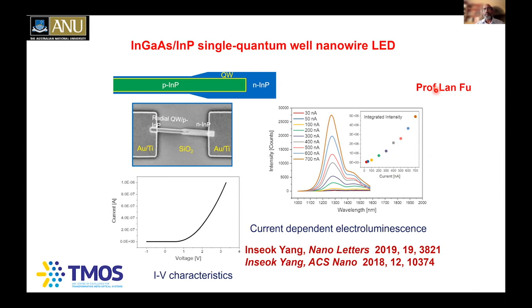So you asked me the question, why? You've got a PN junction, you've got a nice quantum well, you're able to make good contacts, and you're able to show that you've got a good diode. What's the problem? Why are you not able to make lasers? The problem is, you need to make metal contacts in order to inject current into these nanostructures, nanowires. But metals have huge optical losses. Then you create a lossy cavity.